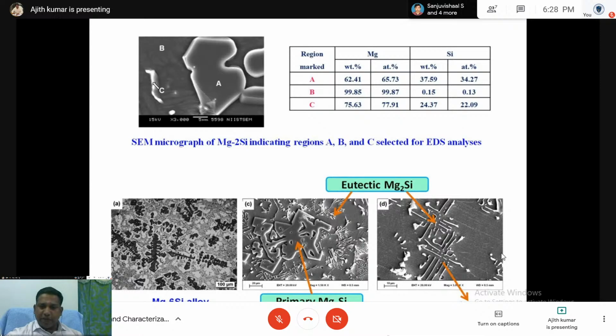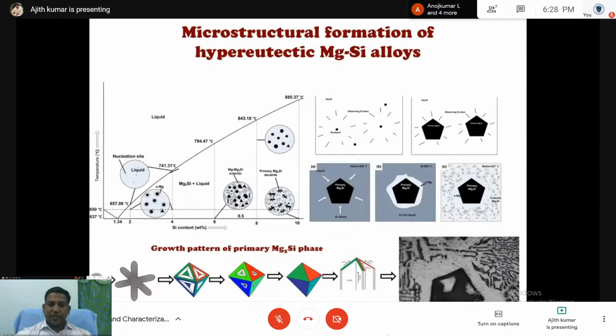In the high magnification SEM picture we can see here, it looks like a Chinese script. So we used to call this structure the Chinese script structure. This is a eutectic microstructure. So all of these structures are forming during the solidification, and we can now see how the structure changes during solidification.